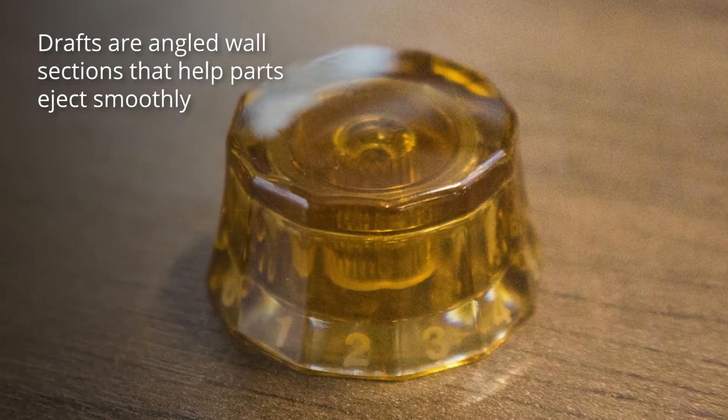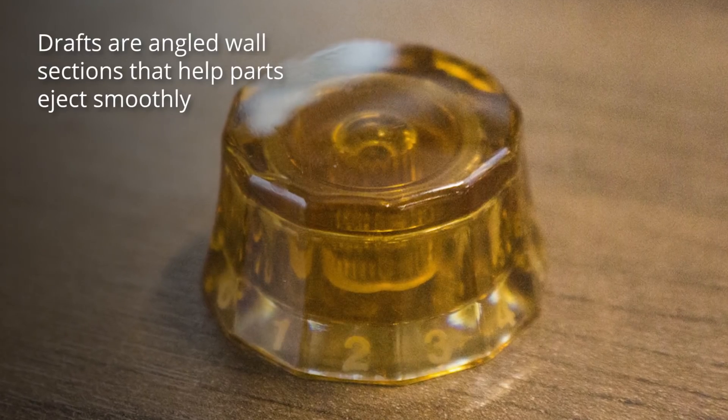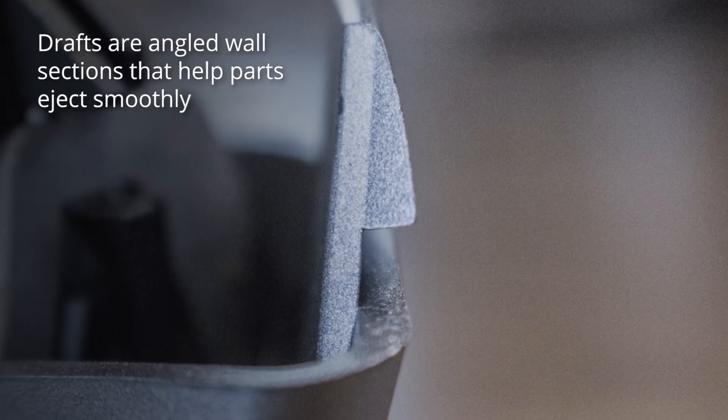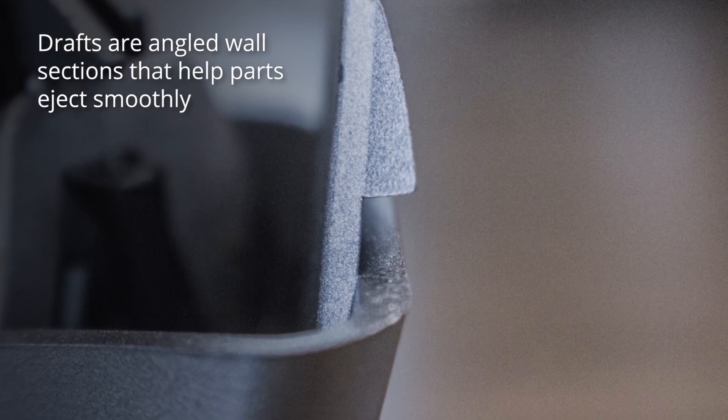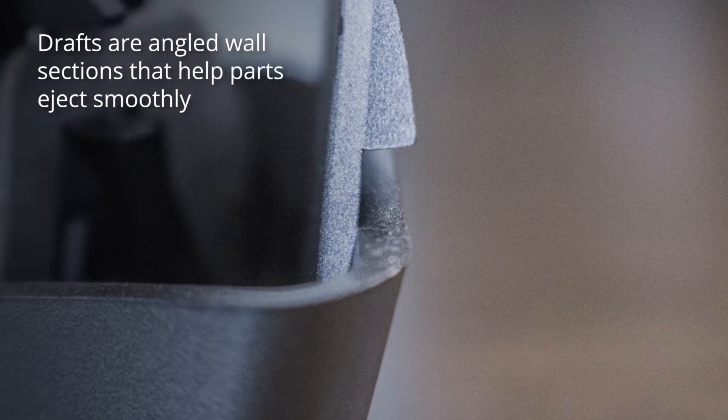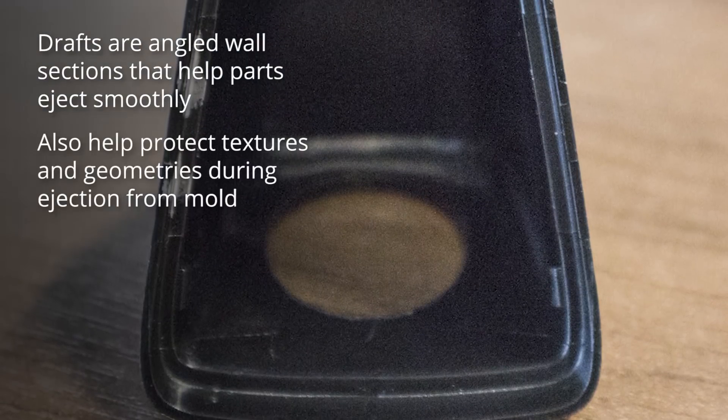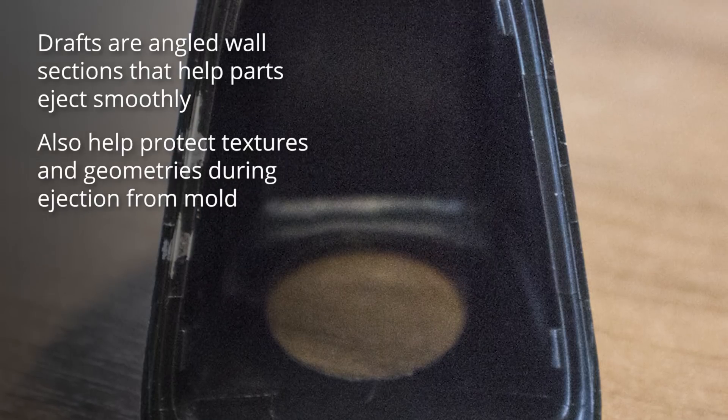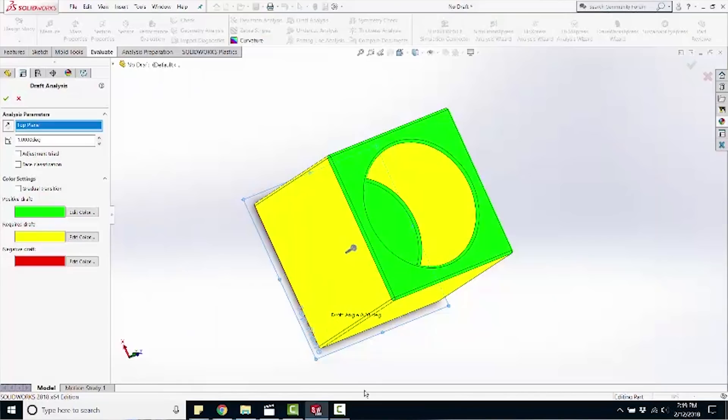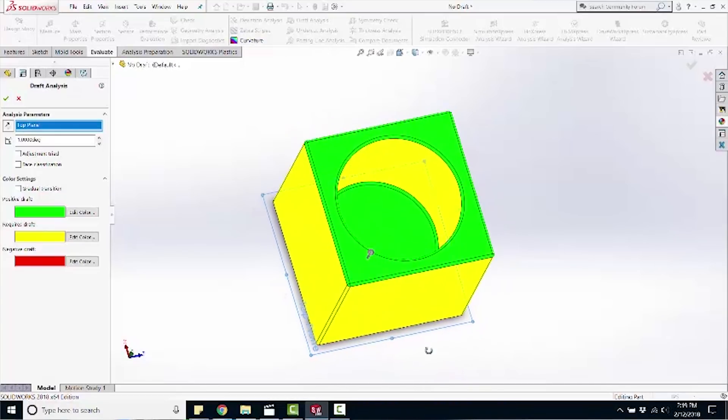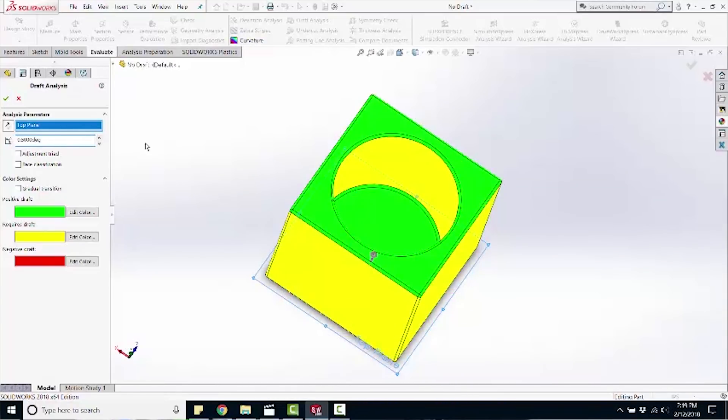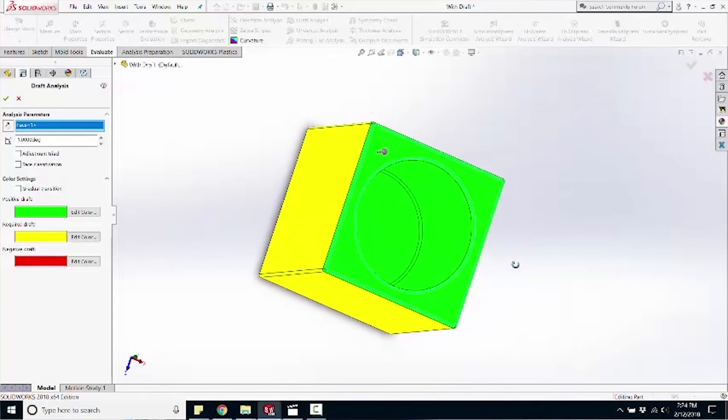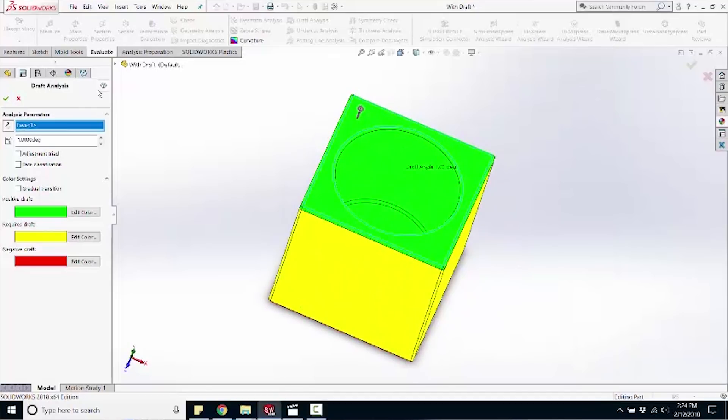Draft is basically angled wall sections. The reason you need to have draft on an injection molded part is that if you don't have draft, the part will not come out of the mold smoothly, and it'll leave scrape marks. Also, if your part is textured or has some kind of geometry, if it's not drafted, it'll rip it right out. So here's a part that is not drafted. If you were to mold this, it would scrape the inner and outer features, and then this coring in the rear, the part would not come out. It would literally interlock. Here, this part is drafted at one degree, and it would come out of the mold easily.